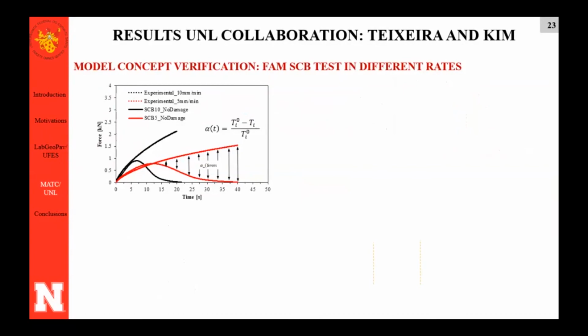So first we need to determine our damage function. Here damage was defined as the difference between the non-damage and the damage testing results. Okay, so here I have the experimental results from a SCB with damage, but I didn't have a test result for the non-damage case. For the non-damage, I basically simulated the same test, but I didn't allow cracks to be inserted. So I would have my non-damage curve.